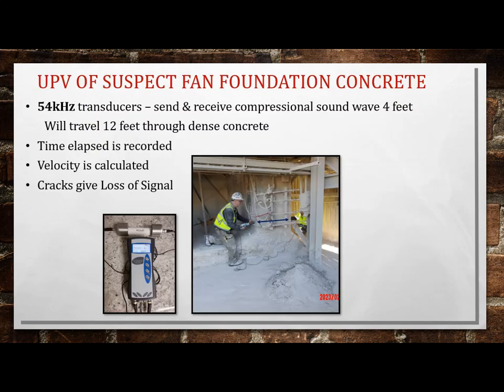Here's an application we were testing: these big fan foundations that just vibrate, and they were full of exterior delaminations. They wanted to know the condition of the inside of the concrete. So we did a series of pulse velocity tests. It's a comparison test. We go to a good area, get a control, and do a series of tests through it, and can locate areas of micro cracking, voids, delaminations, or just generally weak concrete.